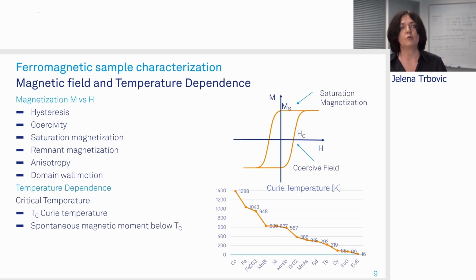In this slide, what I'd like to just remind you is that if we continue further sweeping back the magnetic field for ferromagnetic materials, we will see the hysteresis loop. And from this one loop, we can understand what is the switching field, what is the saturation magnetization, remnant magnetization. We can see if there is anisotropy with respect to the applied field. And we can really understand how we can manipulate this device. We can see the domain wall motion and see if we have multi-domain or perhaps single domain structure in this